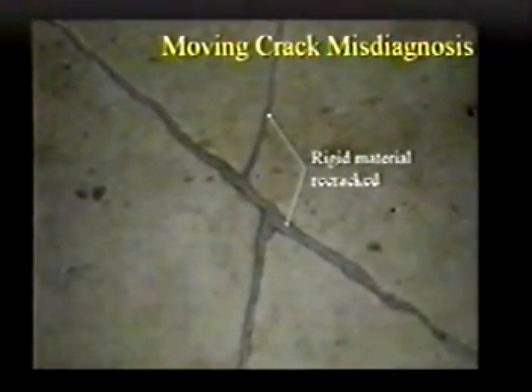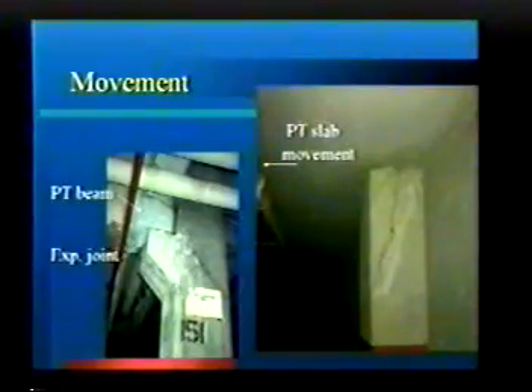Every one of them is now leaking. Sometimes with an epoxy crack, you'll get a new crack right along the existing epoxy, because that epoxy is stronger than the concrete, and sometimes its bond is better than the concrete itself. But this is a misdiagnosis on a crack. Movement, got to be thinking about your movement.